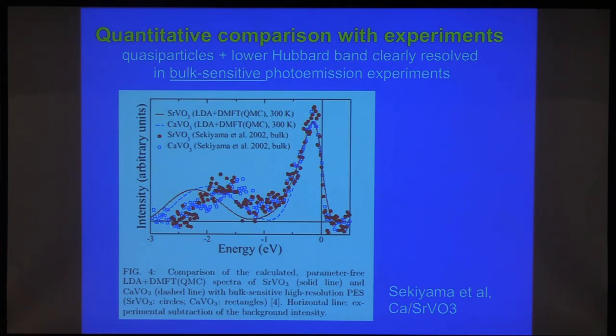And you see that these methods actually do a reasonably good job at predicting both the quasi-particle excitations and the Hubbard satellites accurately. And importantly, the transfers of spectral weight that are seen in all the spectroscopies when you change a parameter like pressure or temperature. And these two kinds of states actually communicate, and describing these transfers of spectral weight is really important.